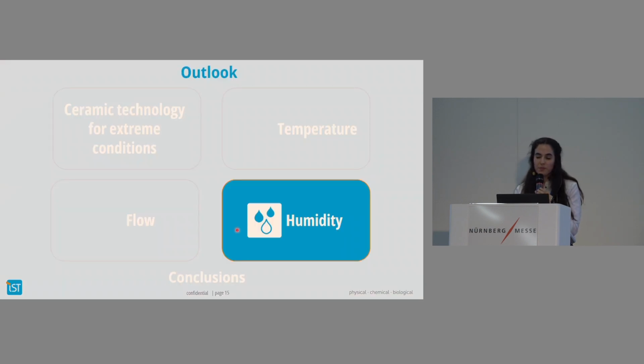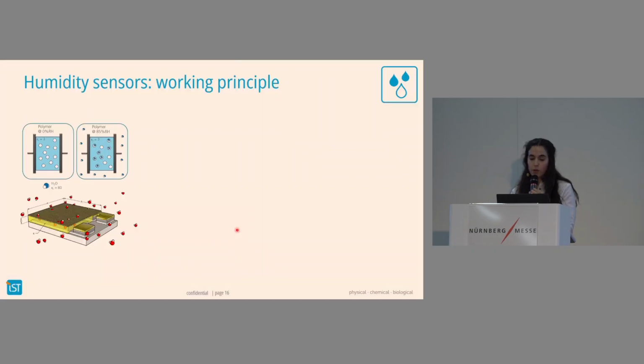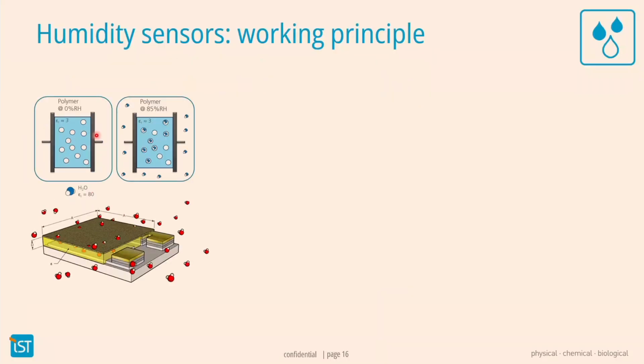For humidity, the question is how we can make this ceramic technology work for humidity. So we base that on a capacitance measurement. We have two plates, basically, and in the middle there is a polymer, and this polymer has the ability to absorb or dissolve water. Now, depending on the amount of water that it has absorbed, it will have a different relative permittivity, and this would give a different capacitance. So here, what we can correlate is the capacitance to the amount of humidity.